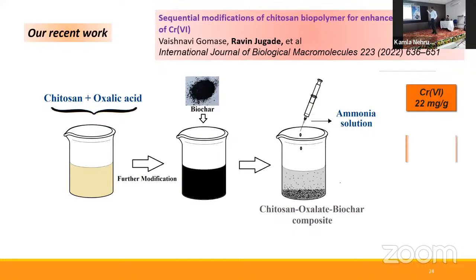There is another dual modification of chitosan with oxalic acid and biochar, and the composite was found to have increasing chromium absorption capacity with further improvements.